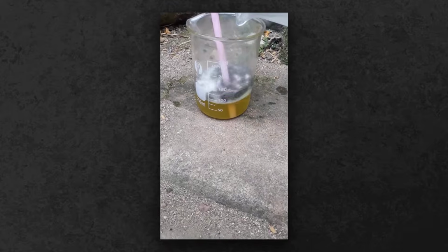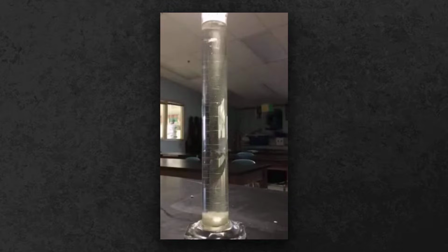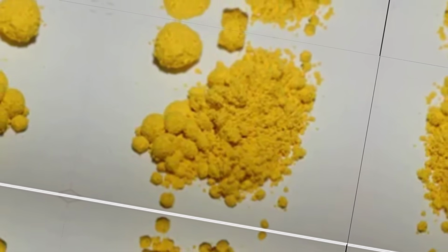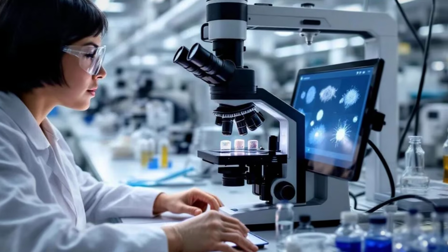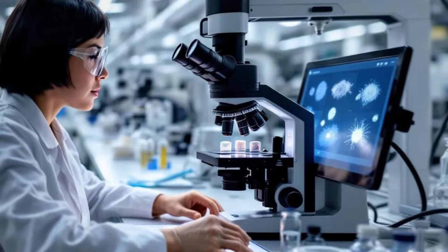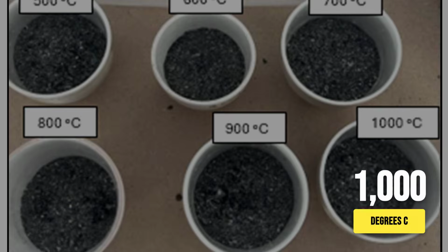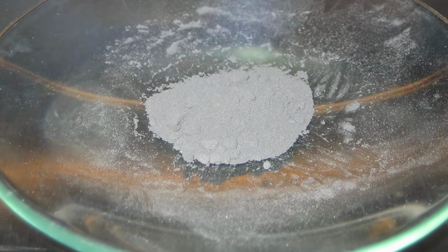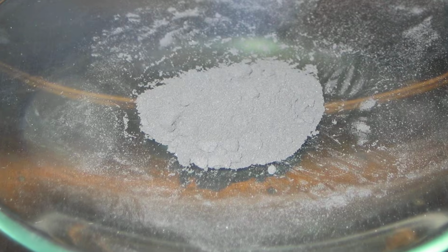Selective precipitation follows. Ammonium chloride is introduced, coaxing platinum to form distinctive yellow crystals of ammonium hexachloroplatinate. These are filtered, washed, and gently dried, with technicians inspecting each batch for color and clarity, signs of purity at the atomic level. The dried crystals enter a high-temperature furnace, where they are calcined at up to 1,000 degrees Celsius. The result is a fine, gray powder, known as sponge platinum.